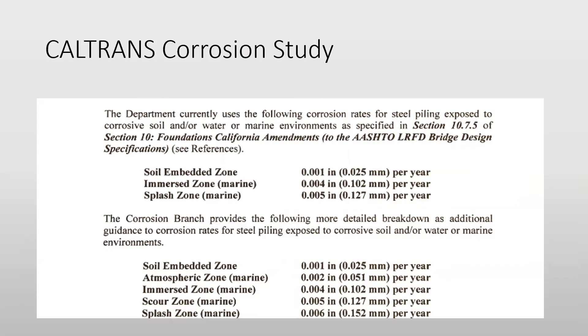The department cited that sacrificial metal be incorporated into the design of the pipe wall thickness to compensate for the loss of metal that occurs due to corrosion. This extra metal thickness is added to all surfaces of the pipe that interact with the soil and water. They classified three different major environments: a soil embedded zone, an immersed zone, and a splash zone, wherein they calculated an estimated wear rate of 0.001 inches per year to the outside of the pipe in the soil embedded environment. As the environment becomes more corrosive, that factor increases. The key point is that this was determined to be compensated by incorporating sacrificial steel into the overall wall thickness of the pipe.